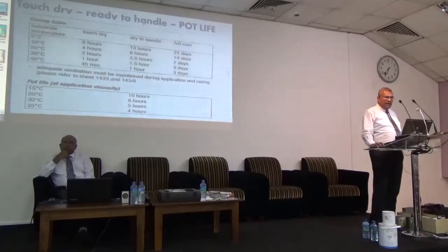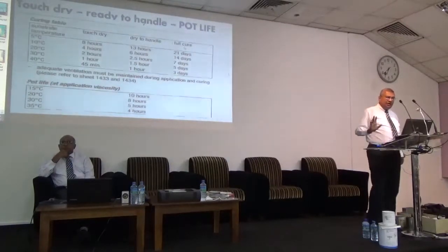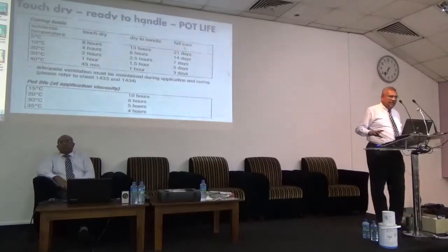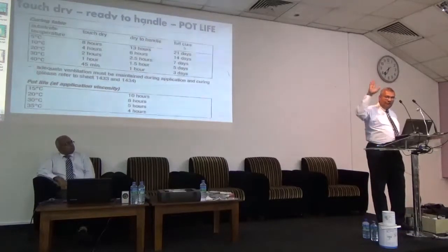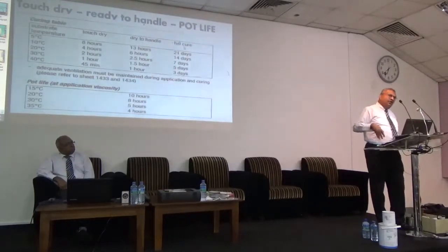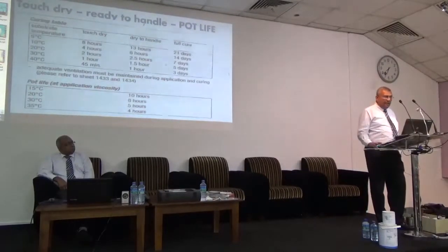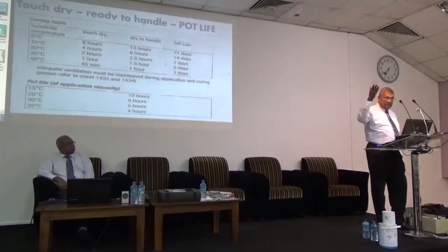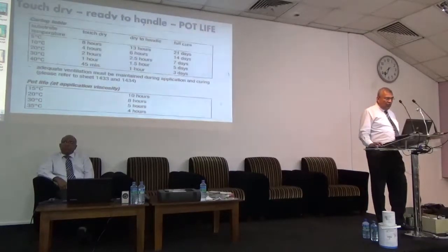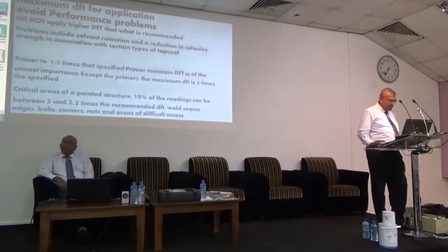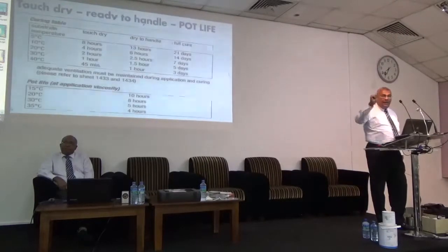Now, full cure I will just explain and put in another slide. Full cure is not a problem for the tank exteriors. You apply a prime coat, you wait for 3 hours, 4 hours, apply a second coat, another 3 hours, put the third coat, and you just look the other side, because the paint will cure. But especially in petroleum, where there are water tanks, after the second coat is applied, if you don't keep 5 days, the paint is not cured.